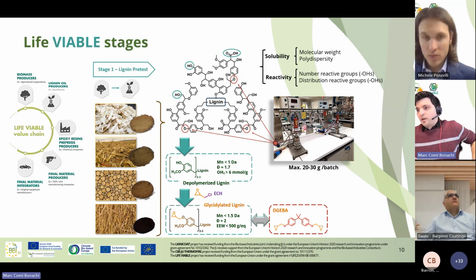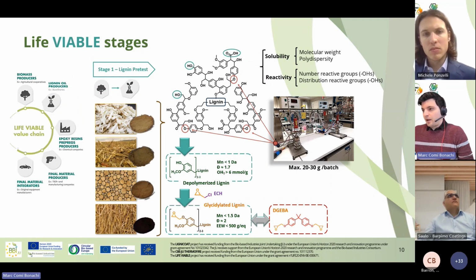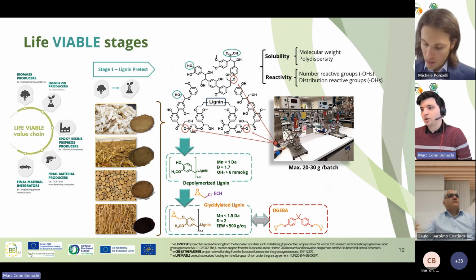What we are doing later is modifying the phenol that we created by the break of the beta-O-4 ethers with epichlorohydrin, creating the glycidylated lignin. It's very important for us also to measure the epoxide content in order to make it comparable with the commercial diglycidyl ether of bisphenol A.